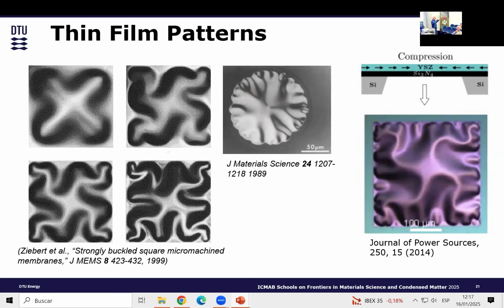What happens is that you take a membrane. These are metallic membranes. What you see here, you make a membrane on top of a window of silicon. And the material tries to relax, and it relaxes by forming a buckling mode. This buckling mode is not arbitrary. These are well-defined. It depends on the thickness, the shape, and the material. So for a circular shape, you will get some buckling mode in this way, and for a square, you will get something like this.